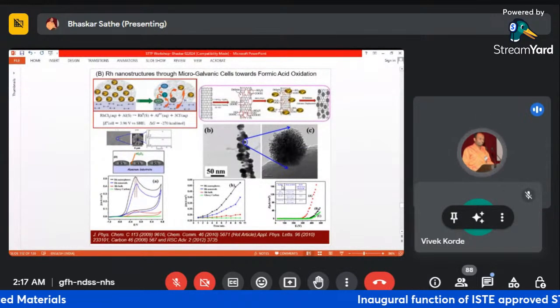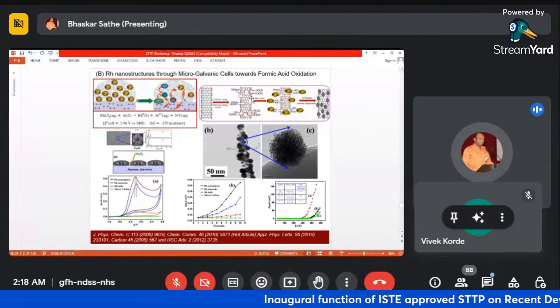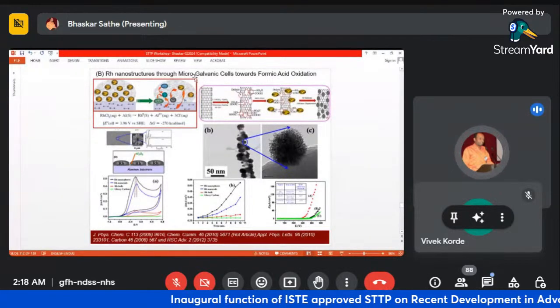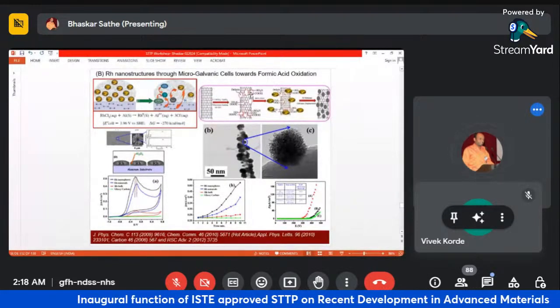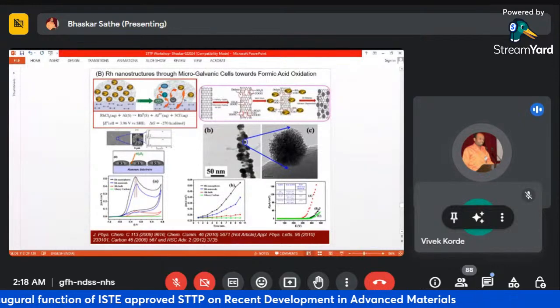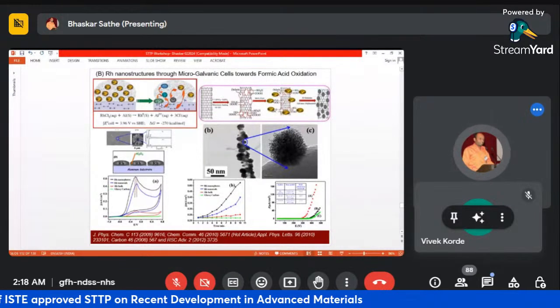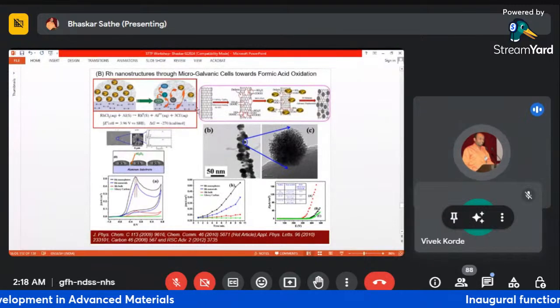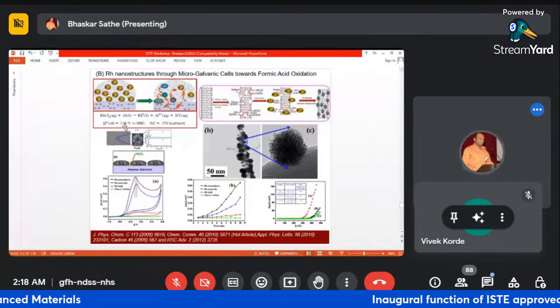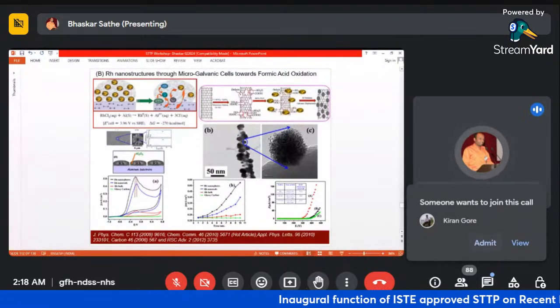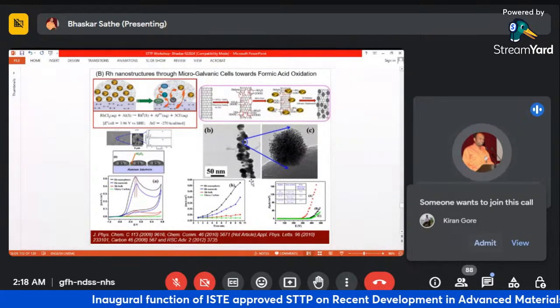Again, we have modified the carbon nanotube with rhodium nanostructures by making pockets on it, and by the galvanic approach with aluminum, we have exchanged this with the rhodium 3 plus ions because of the difference in the potentials. So we got a systematic decoration of clusters of nanoparticles on the surface of the carbon nanotubes.